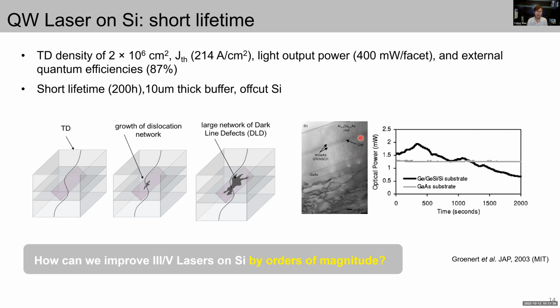So in addition, if you want to further lower the threading dislocation density below this value, this is very difficult. Since the interaction between the dislocations is the only mechanism to filter out the dislocations in both films, with such a low threading dislocation density, the possibility of two dislocations meeting each other to annihilate is extremely low. So defect-free III-V on silicon, or even defect levels comparable to that of state-of-the-art III-V wafers, will theoretically never be available. So in this scenario, how can we improve III-V lasers on silicon by orders of magnitude?